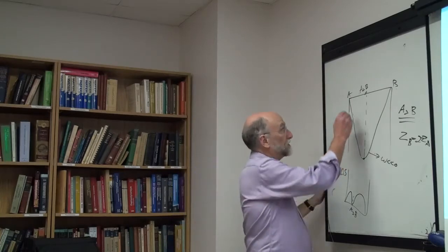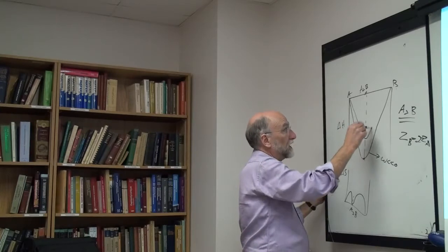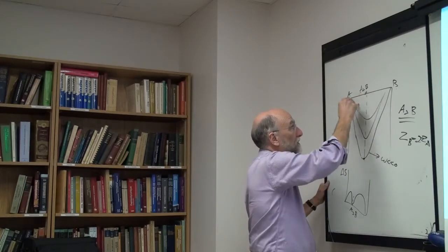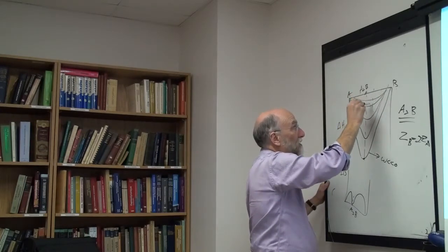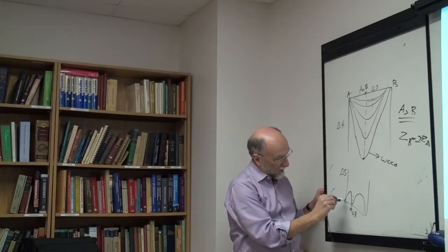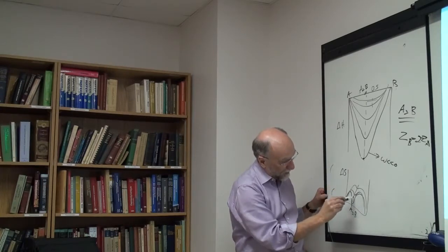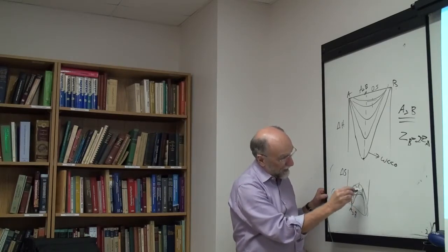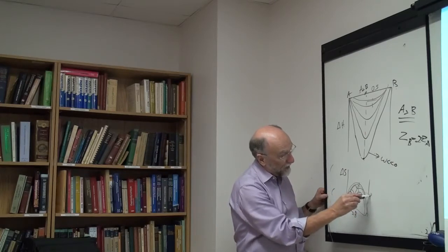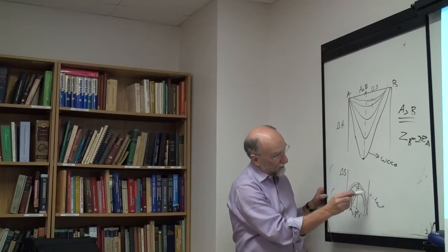So as omega becomes less negative, the peak becomes less sharp, but at the same time the minimum point moves over towards 0.5. Similarly for the entropy: as omega becomes less negative, the peak becomes less sharp but moves over, so that once you get back to the ideal limit of the entropy, the minimum is at 50%.